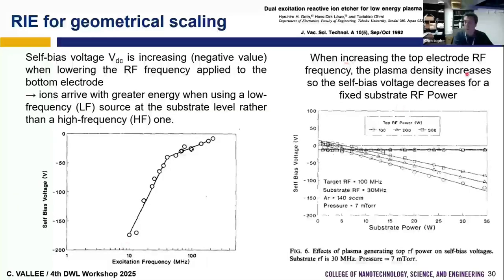And for the top electrode, they also studied that if they modify the radio frequency and they go to high frequency, they can increase the plasma density. And they look at how it will impact the self bias. If they increase the plasma density, for example, from 100 watt to 300 watt, the DC self bias will be lower for a given power to the substrate, and the ion energy will be lower because, again, if we have a more dense plasma, we flow more current, so the power at the substrate will develop less voltage, so less DC, so less energetic ions.